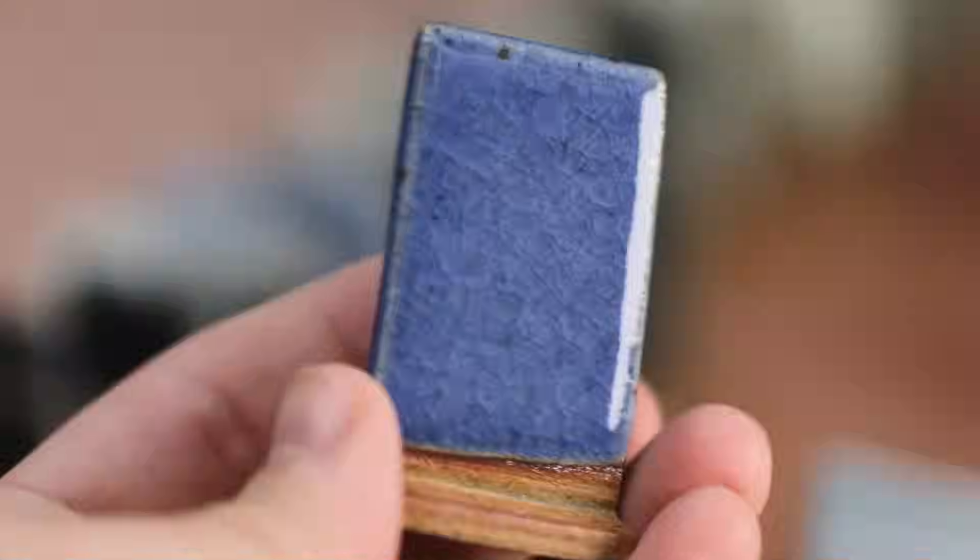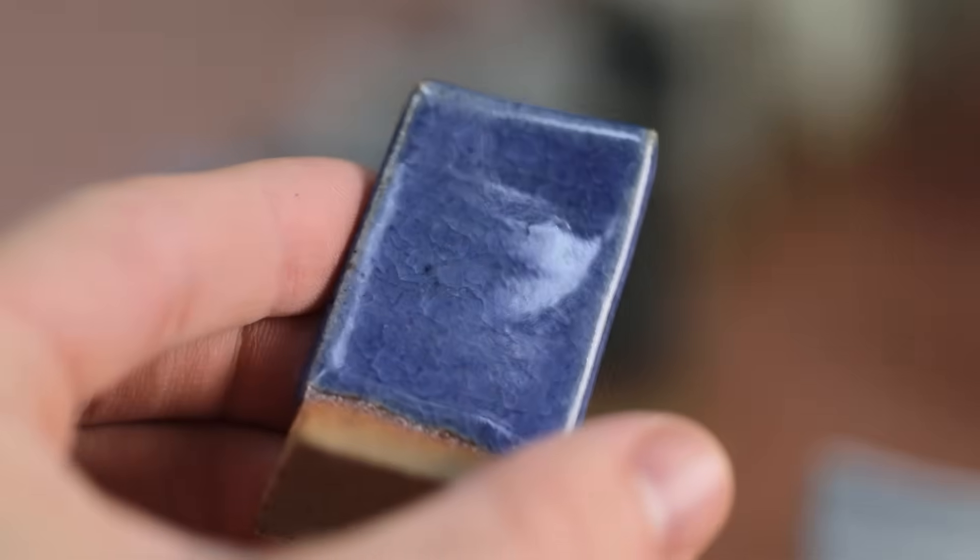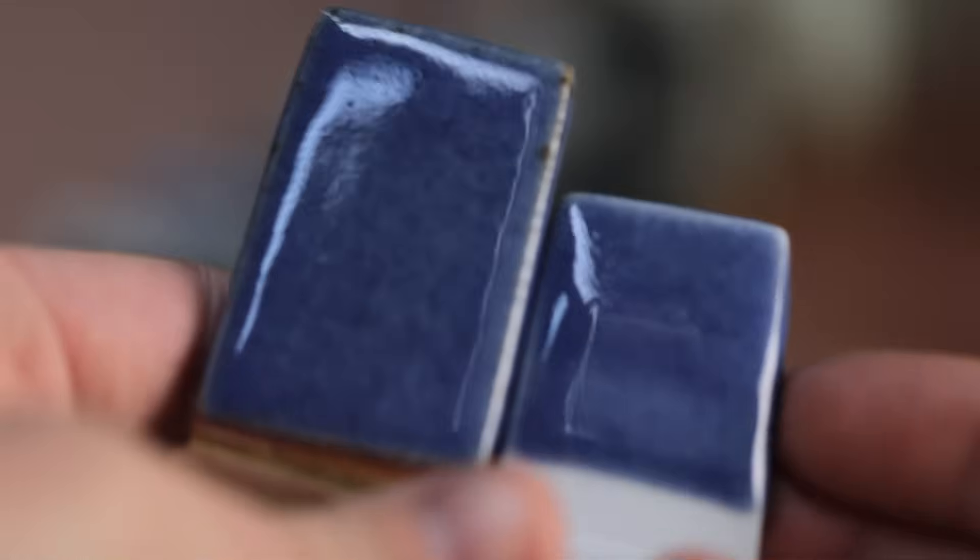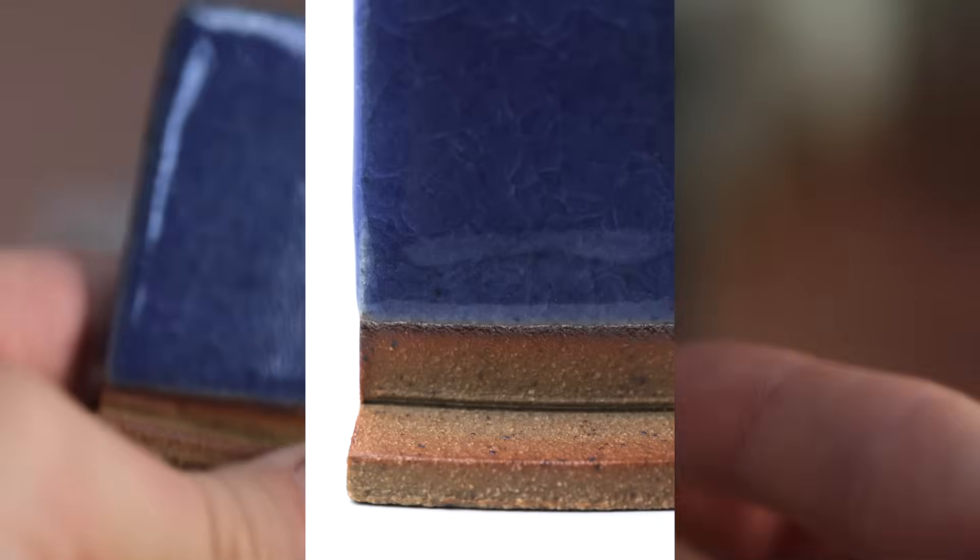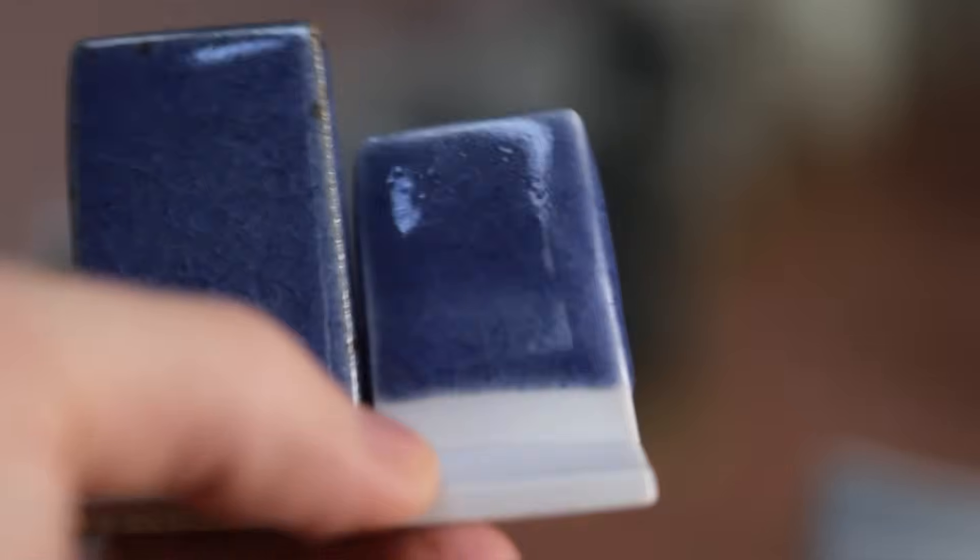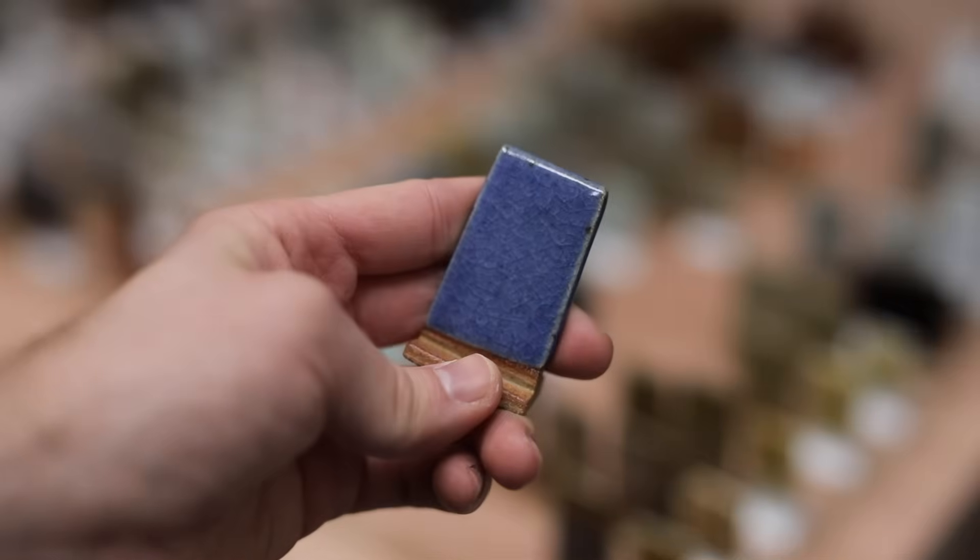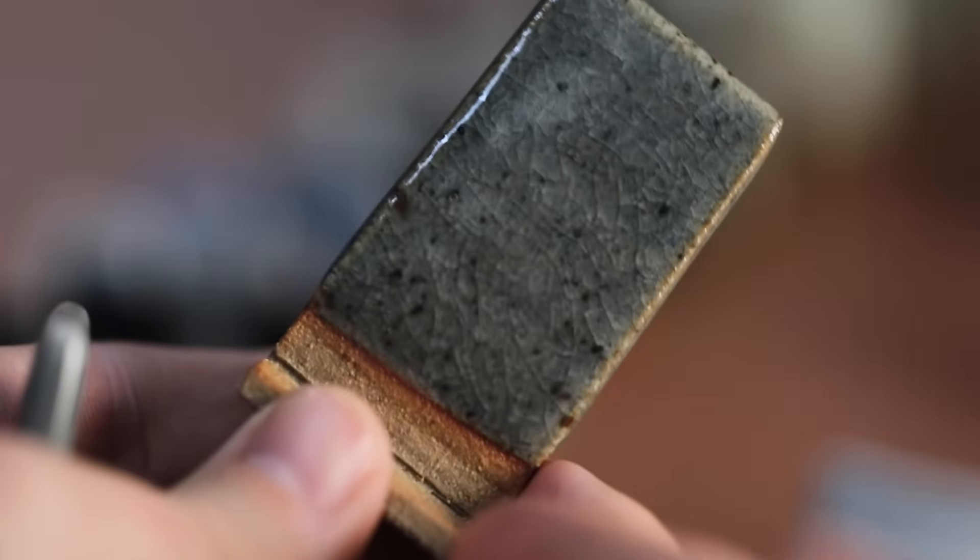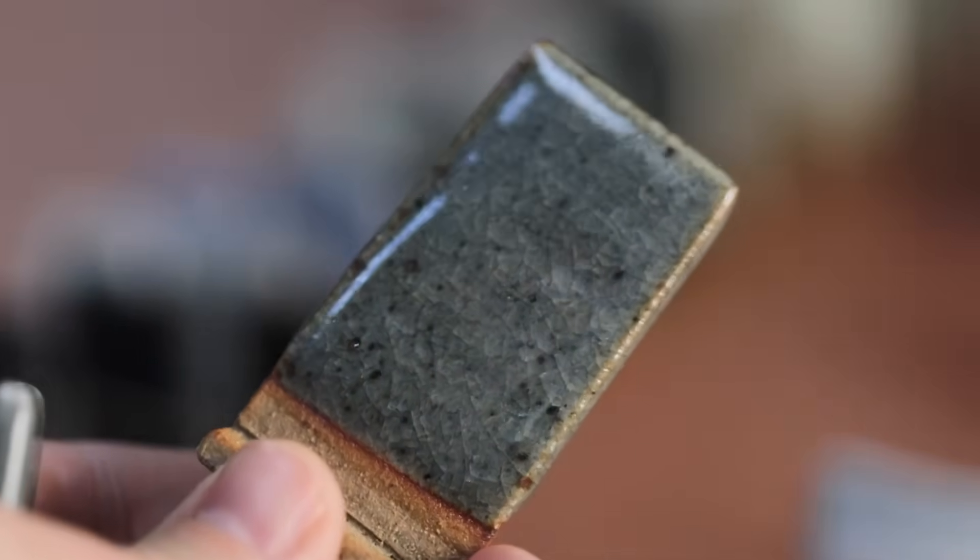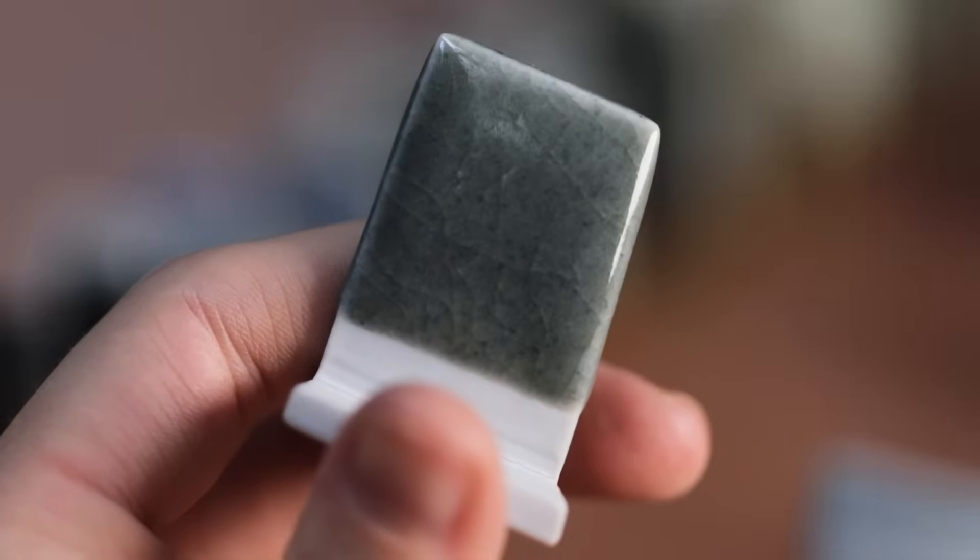This first one is simply the white base, but with an addition of 0.5% cobalt oxide. And whilst it is quite vivid and rather fantastic, I don't think it fits too much into my palette of colours. I know this cobalt colour seems to be rather trendy at the moment, but it simply isn't for me. It's incredible how potent cobalt oxide can be though. After this initial test, I dialed back the amount I used, and in doing so I was able to create some rather nice grey tones, such as this, which simply contains 0.1% cobalt oxide, which I like, and I like it on porcelain too.